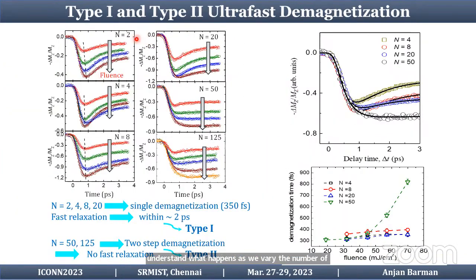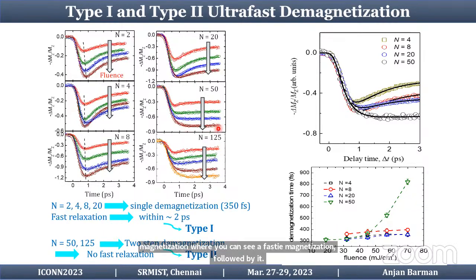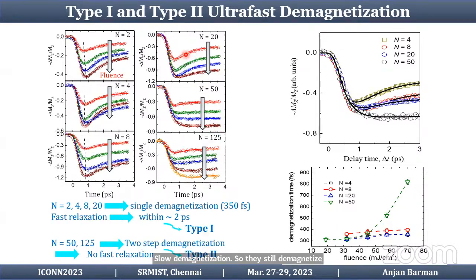So this is the data, and you can see that for n equals 2, the down arrow shows that the fluence increases along this direction. As the fluence increases, the overall quenching increases, but it remains a one-step demagnetization, or type 1 demagnetization. As n increases, this remains the same, but as we go to n equals 50, instead of a single-step demagnetization, you go into 2-step demagnetization, where you can see a fast demagnetization followed by a slow demagnetization. This still demagnetizes. It doesn't recover, unlike here, for example, where there is a demagnetization and recovery. Here there is a 2-step demagnetization, called type 1 and type 2 demagnetization. The same occurs for n equals 125.